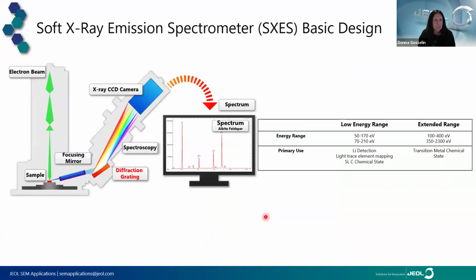That second soft X-ray emission spectrometer, there are 2 versions of it. Low energy range, optimized for light element analysis, is perfect for battery applications. There's also an extended range system that is more optimized for transition metal chemical state. Looking at the schematic here on the left, the system works by using a focusing mirror to collect the X-rays on a diffraction grating where the wavelengths are separated and detected with an X-ray CCD camera. And the spectra are displayed much in the same way as an EDS spectrum.